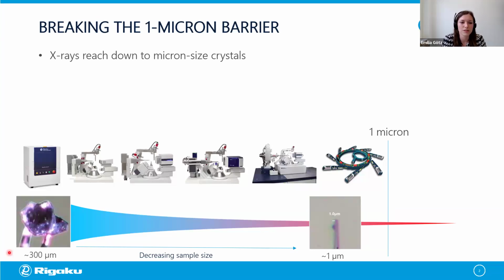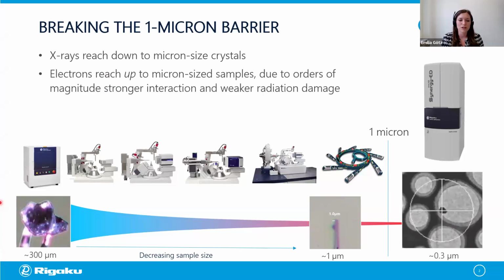And as you certainly know, X-ray diffraction gives you access to crystal sizes down to 1 micron. And here you can see the portfolio of instruments of Rigaku Oxford Diffraction, all the way from a benchtop instrument to the high-end instrument and even a synchrotron. But there's a certain barrier of 1 micron, and below that it becomes very difficult to get a good diffraction signal out of single crystals. And for electrons, a 1 micron crystal is essentially a beam stop because electrons interact many orders of magnitude more strongly with any matter, which means that even with tiny crystals, you can get sufficient signal to solve a crystal structure from a single crystallite the size of a powder grain.